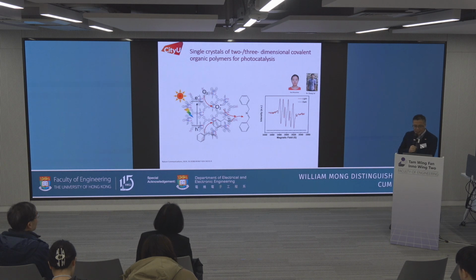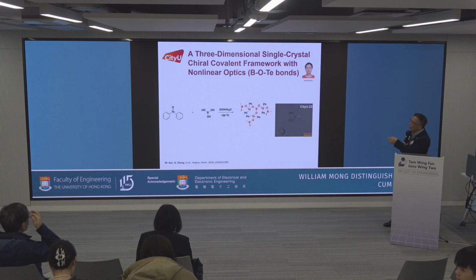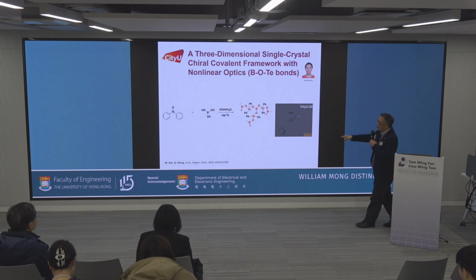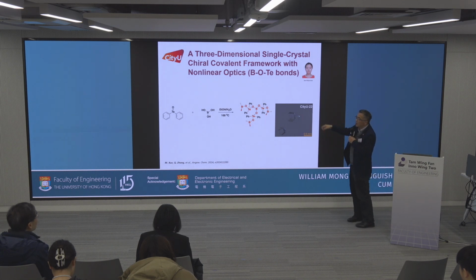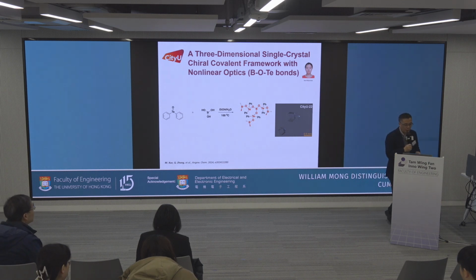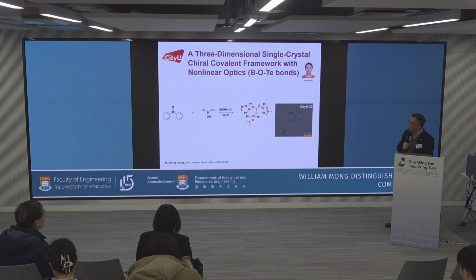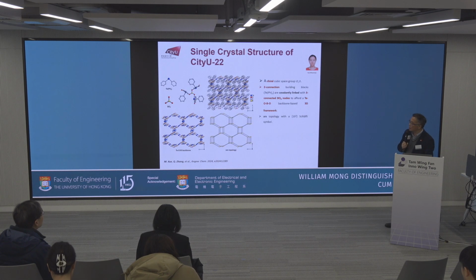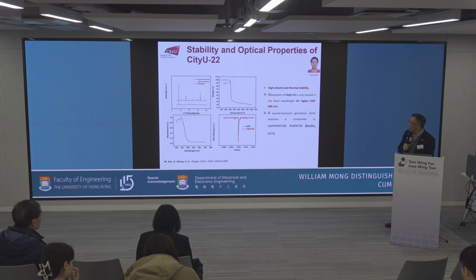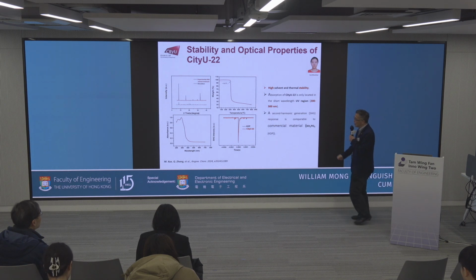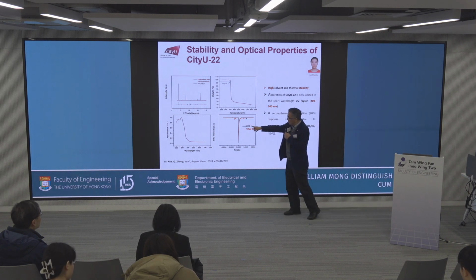Besides this system, we also try to use the diphenyl tellurium oxide to react with boronic acid. It looks like things work very well. And then we solved the crystal structures. Actually, this is a 3-dimensional framework, and we do have a non-centrosymmetric structure here. So we measured the nonlinear optical property as shown here. You can see our material is very similar to the commercially available KDP.